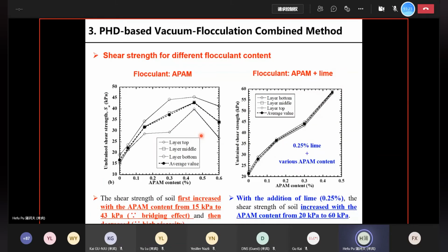In addition to the dewatering efficiency, if we look at the strength, adding the flocculant and the vacuum pressure also can increase the shear strength significantly. We look at different flocculant. On the left, we have used APAM. On the right, we used APAM and also lime, some kind of composite flocculant. On the left, we can see that the shear strength of soil first increased with the APAM content from about 15 kPa to 43 kPa. That's about 2 times increase because of the bridging effect of the flocculant.